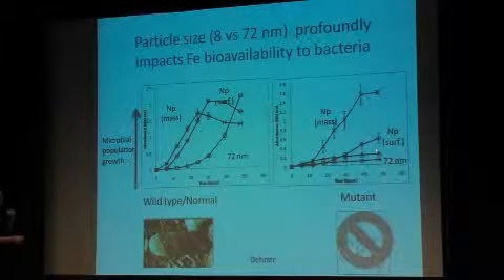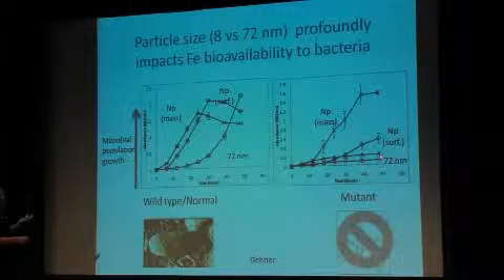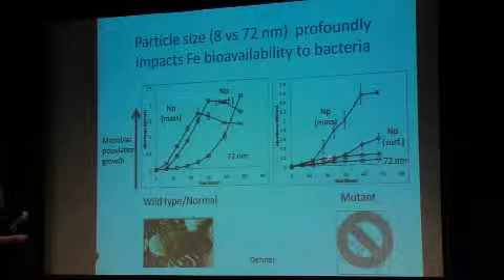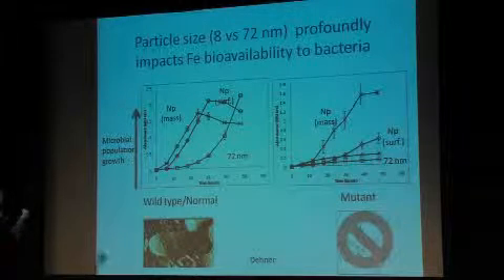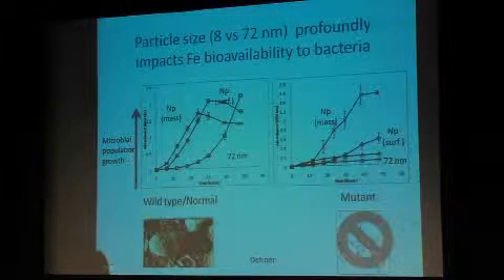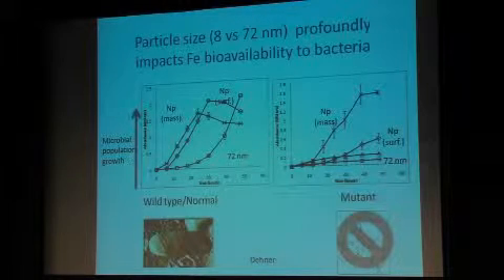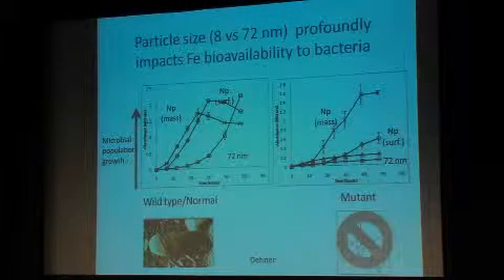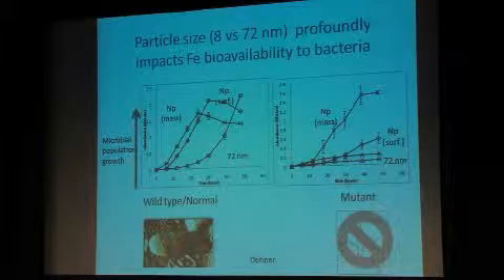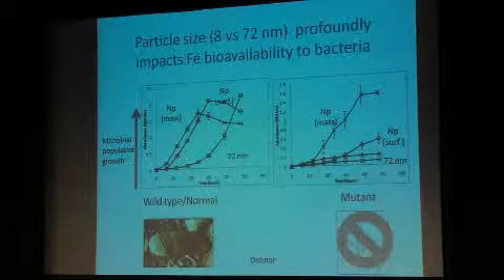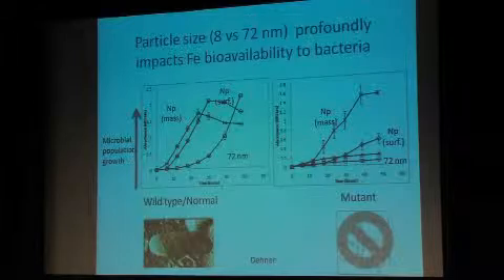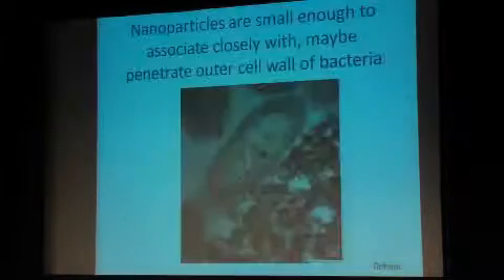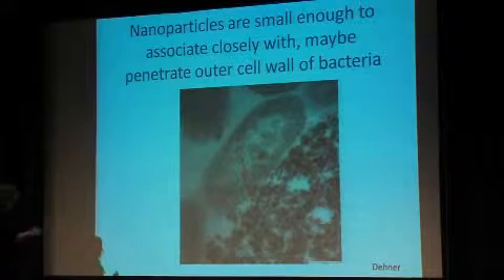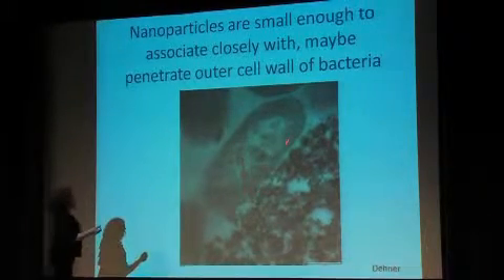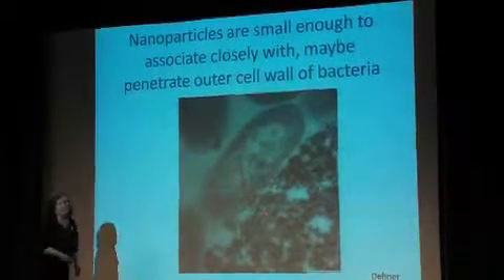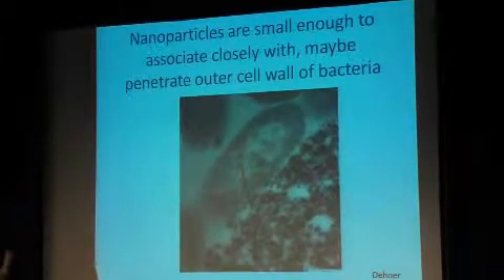The larger particles that can't get iron out, they can't grow. If you normalize the surface area, they can grow a little bit. If you normalize to mass, they can grow tremendously. These bacteria can use a totally different mechanism for getting iron out of tiny nanoparticles than they can out of the larger particles. And the experiment gives different results, whether you add the same mass, which is different surface area, or you add the same surface area. Some of this is that these nanoparticles actually can attach to the cell wall and maybe even get into the cell wall, and we know that there's a cell wall associated reductant.